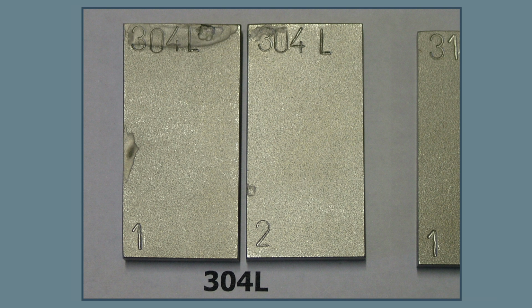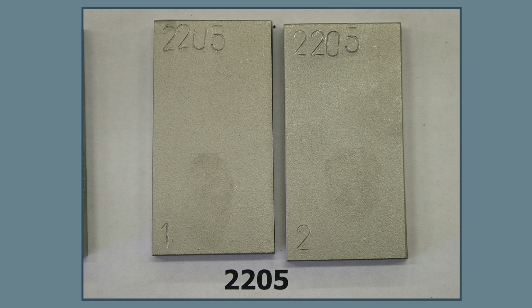So these are the coupons that we exposed in those vessels, and we could see the pitting corrosion at the top of the coupon and on the sides. And then one of the additional alloys that we looked at to try and up alloy is the 2205, which showed quite a bit of resistance to this type of attack. And that's what we went with in the end of the day.